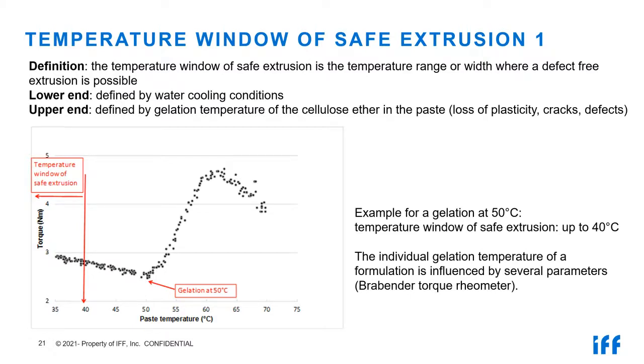So I said the lower end is defined by your water cooling conditions. The upper end, however, is defined by the gelation temperature of the cellulose ether in your paste. There are 5 origins which contribute to the gelation temperature, and they are very individual, depending on 4 recipe parameters and 1 processing parameter. And this is just an example. Next slide.